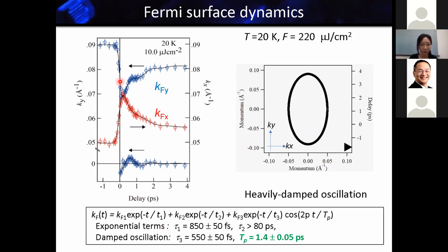The first term shows that this circular Fermi surface goes back to the elliptical shape in 850 femtoseconds. And on its way back in this recovery process, there is oscillation with a time period of 1.4 picoseconds, and the lifetime is about 500 femtoseconds. So by doing this fitting, we can derive this relaxation time of 850 femtoseconds, and this oscillation time with a 1.4 picosecond period.